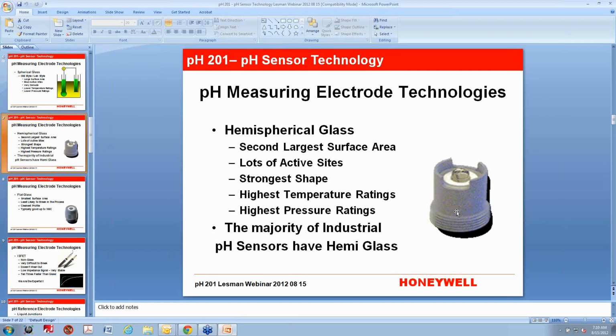And that is going to be your strongest shape. So if you have a really high temperature, or if you bump it, it's going to be less likely to break along that weld line. It has the highest temperature and highest pressure ratings for a glass measuring electrode.